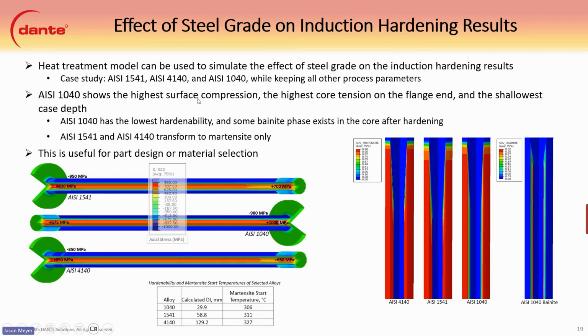And so the results show they are all in the same range as far as the residual stresses afterwards. There isn't very much change between the three different types of models, but we do expect with a higher carbon, like say 0.6, or even lower carbon, 0.2, we may see some very different results here in the residual stresses. But since they all are about the same carbon, they all behave relatively similarly.